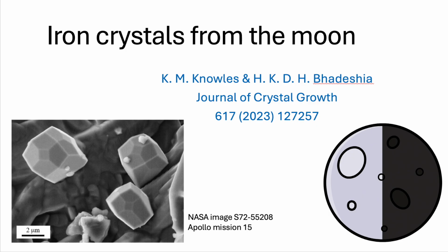If you look at pure iron crystals made in labs here on Earth, or standard iron in most meteorites, they follow the rules. Simple shapes. Predictable shapes. Very predictable. Their morphology, their shape, is governed by these low-index crystallographic planes. Mostly the familiar planes. Right, the standard crystal faces. Exactly. In crystallography, we call those the stable or preferred growth faces, at least in a terrestrial setting. But the lunar samples, they just threw the rulebook out.